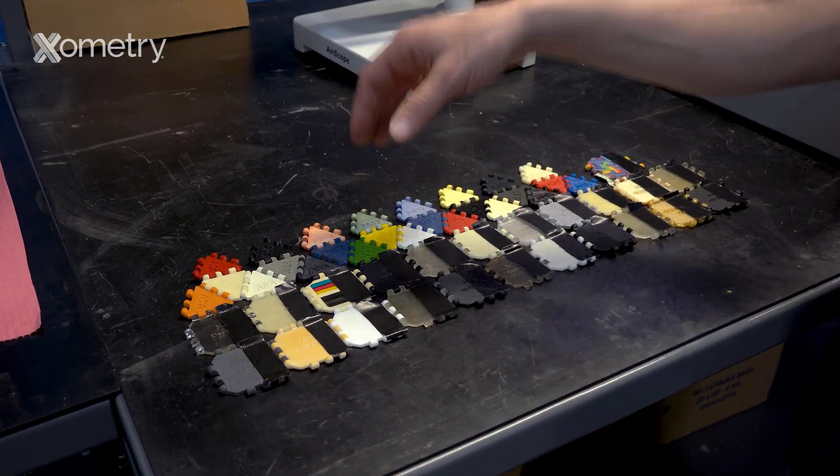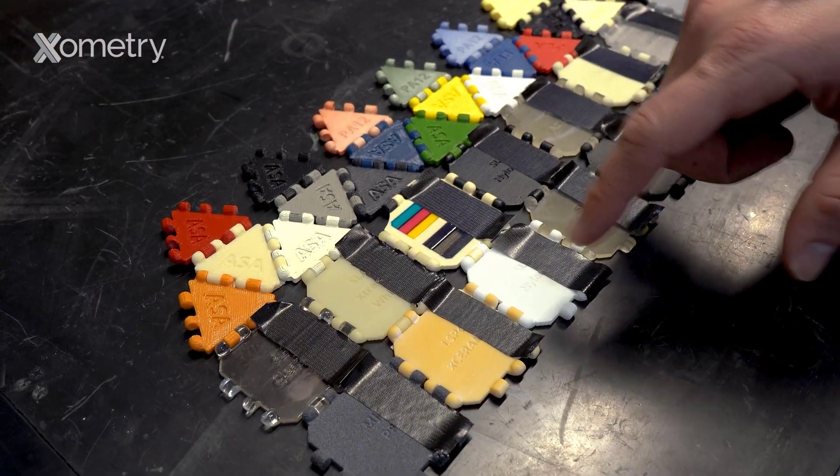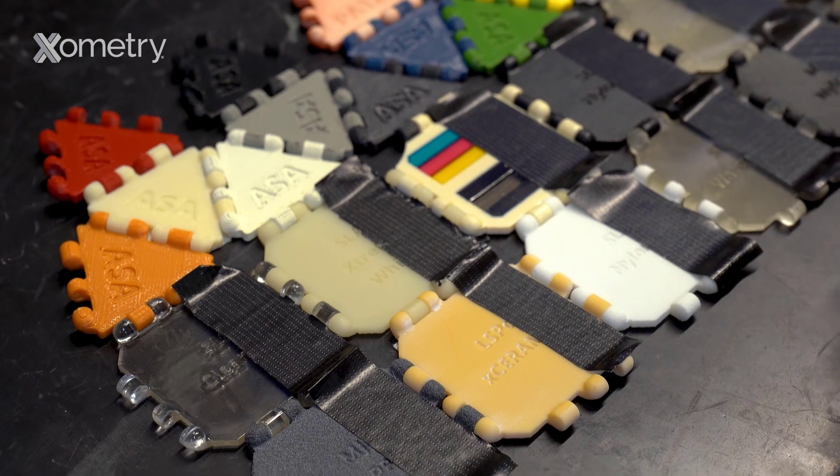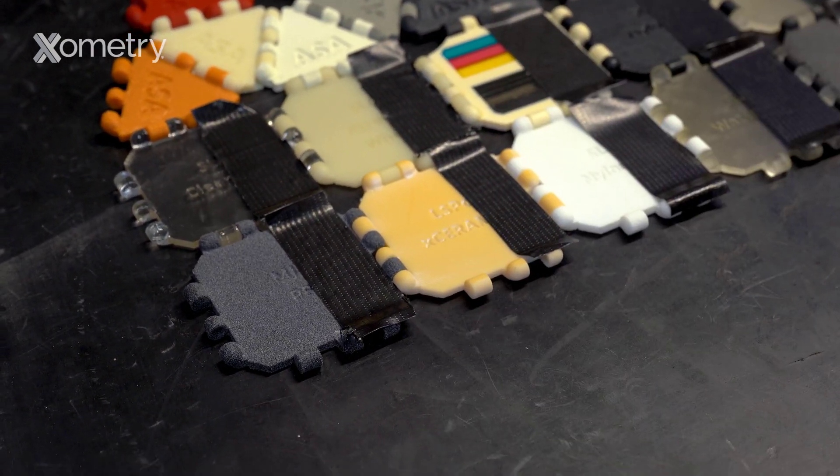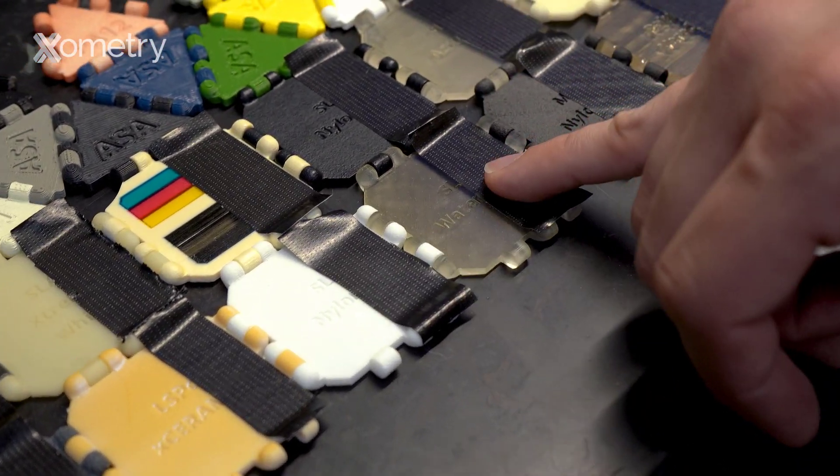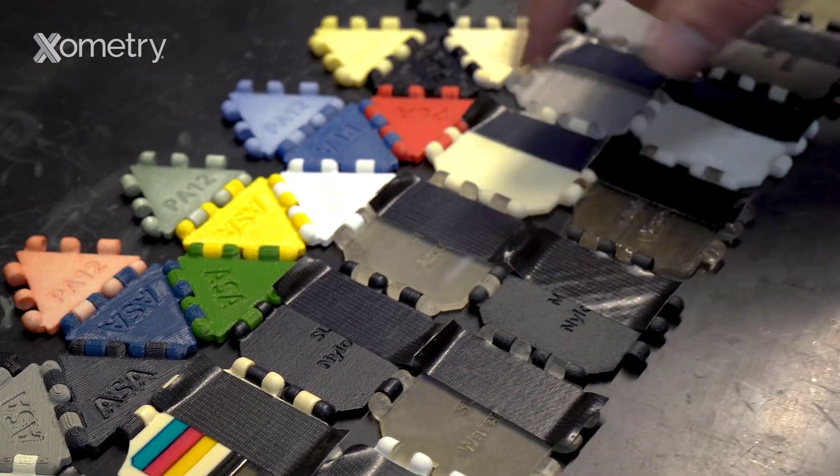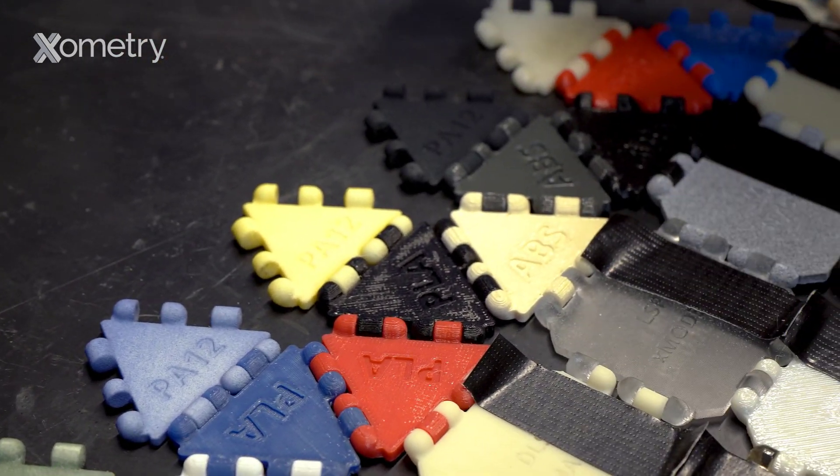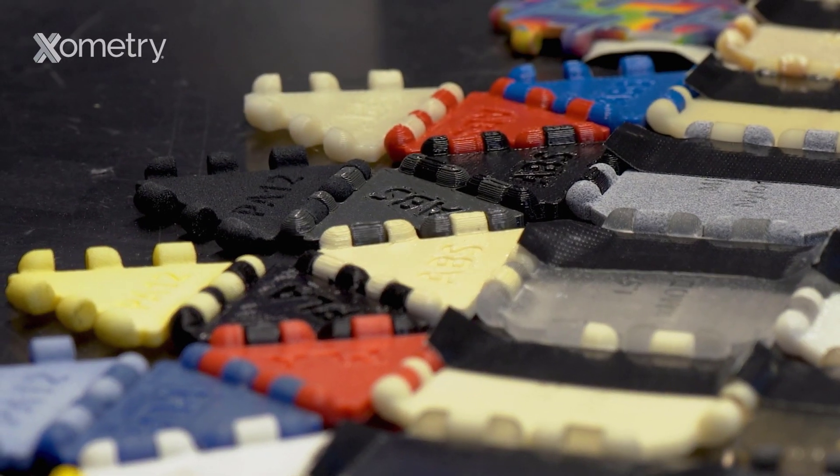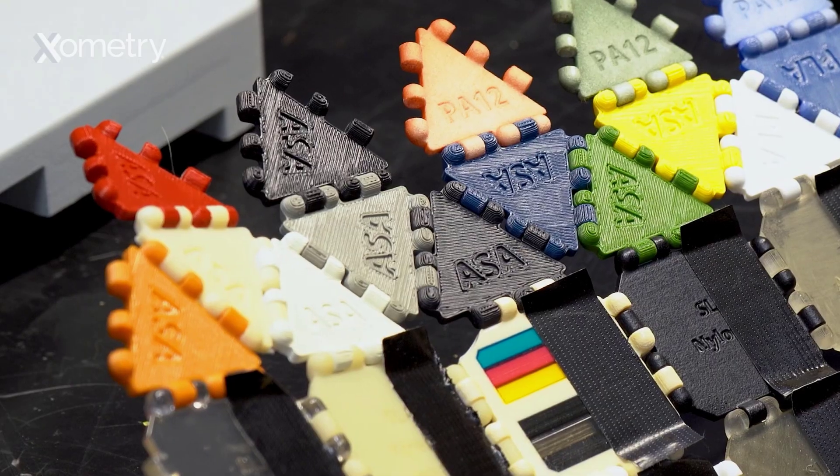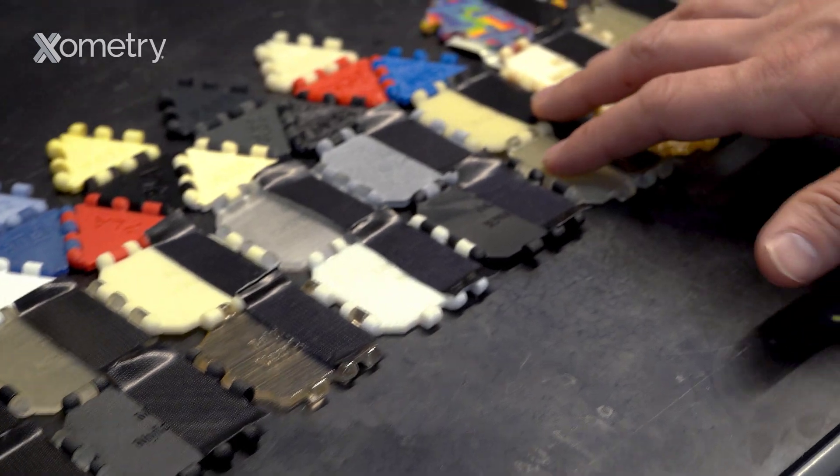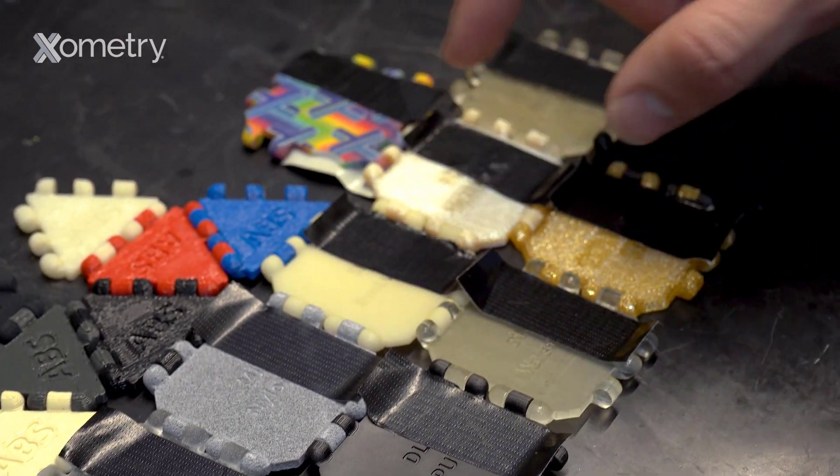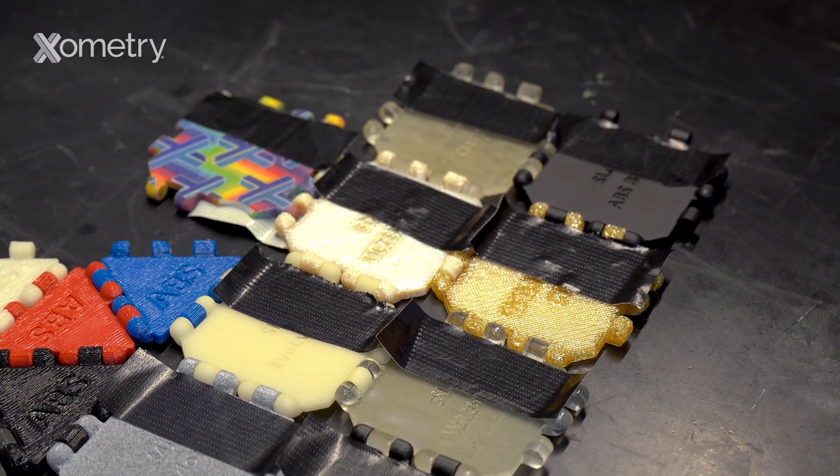This is kind of a stopping point before we finish up for the full week here. Something I'm going to notice is that the resins, so those resin-based photopolymers, are going from a white to more of an ambery or dark cream color here. Especially the X Ceramic is going that brick red. Our clear materials are also showing a movement from clear to more of an amber shade. I really want to highlight though that dye is not surviving. Dye has really faded out. So red, green, blue, yellow dye have all faded out here. Our white ABS is going from white to cream, where PLA and ASA are staying there, although ASA is starting to show some fading, which is surprising. Moving over to the right-hand side, I really want to note that MJF nylon, funny enough, looks unfazed. I'm interested to see what that's going to look like after a week. And FDM Ultem is also looking unfazed. So curious about the results after a few more days.